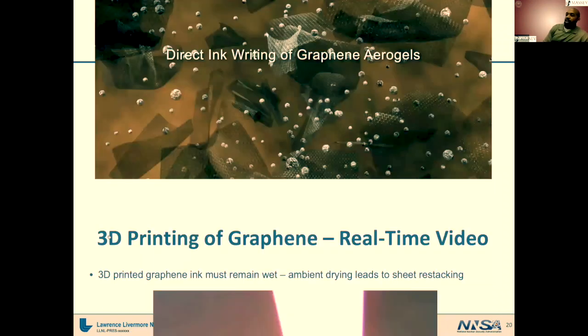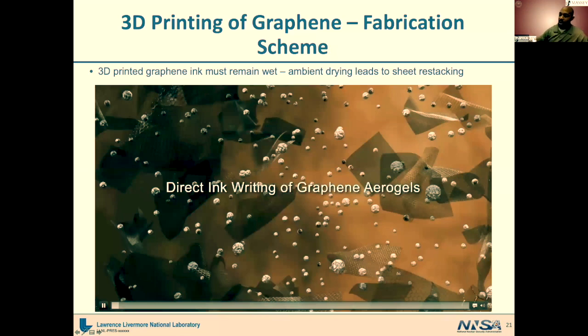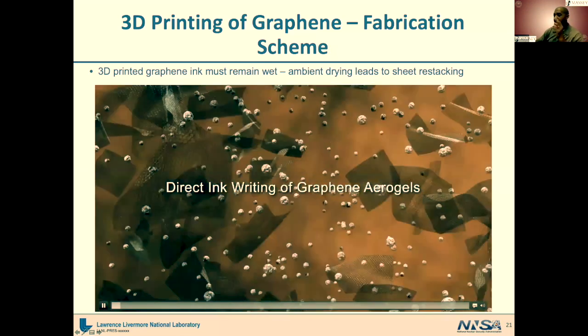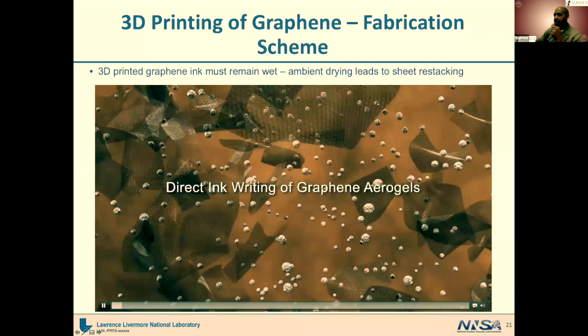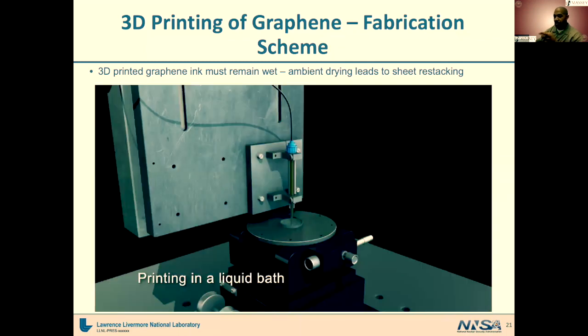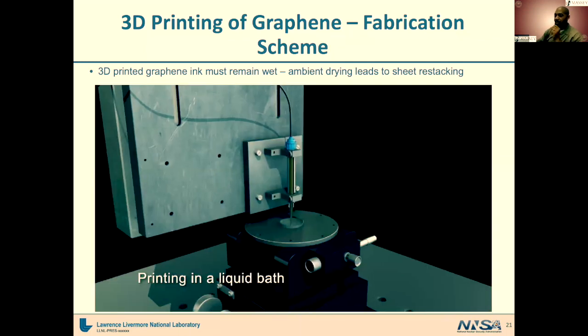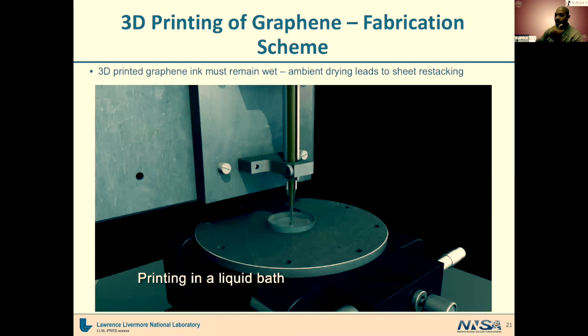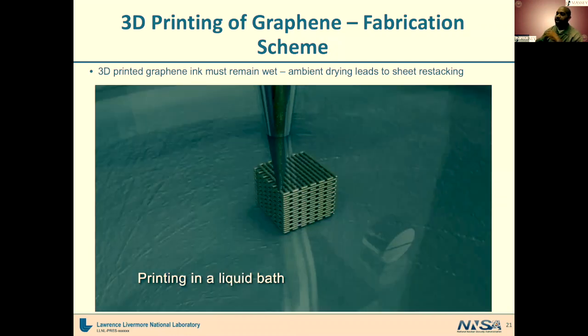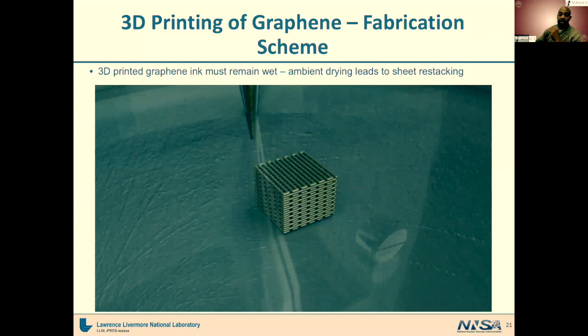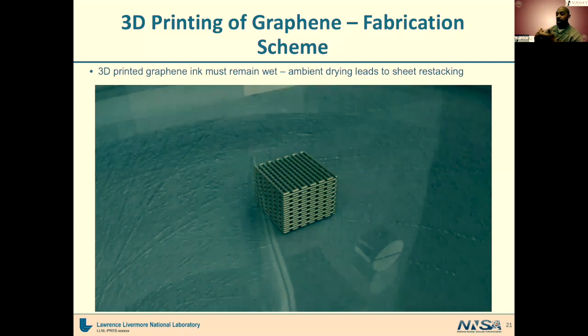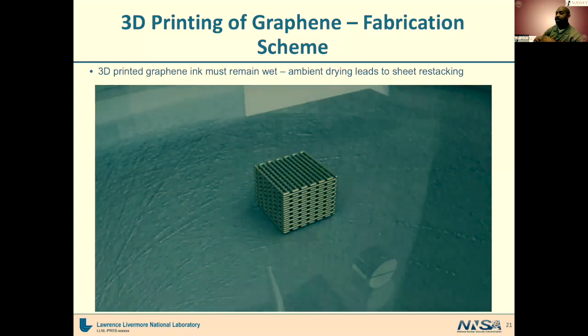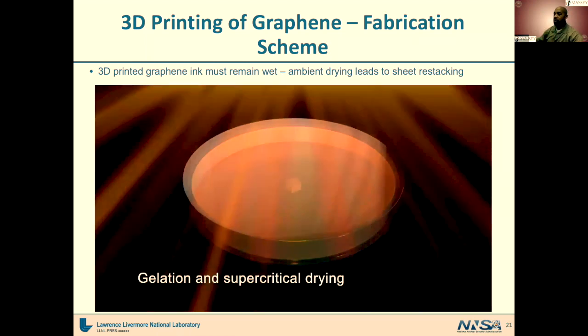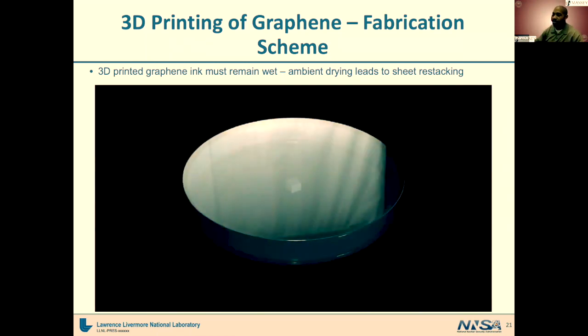The way in which direct ink writing works is you start off with this ink, you put it into a nozzle. You then force the liquid through the nozzle. It comes out as a liquid, but then once it comes through the nozzle and is no longer being sheared, it goes back to being a solid. We do this into a liquid such that the liquid within our gel, or within our ink, does not evaporate and cause premature restacking and shrinkage.